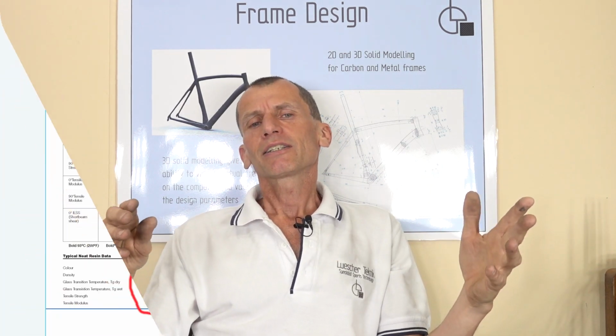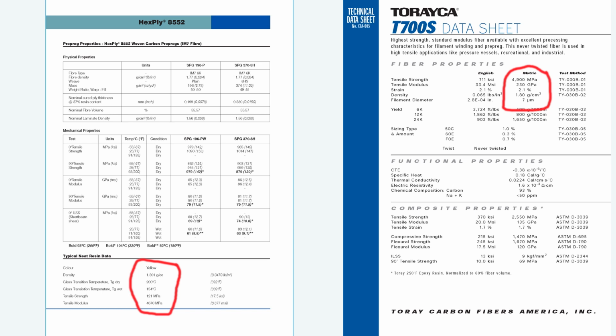So the product still needs to be built well. So no voids, no wrinkles, good fibre content, etc. So typically, with currently available materials, your fibre is around between 40 and 80 times the tensile properties of the resin. So obviously it depends on the grade of fibre and the specifics of the resin. There's so many different resins out there, and different price points, etc. But then even if you double the properties of the resin, you're only making a small difference to the overall tensile properties.